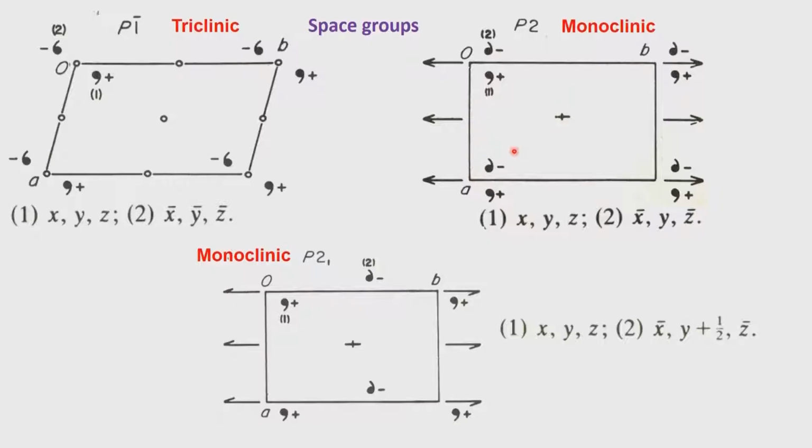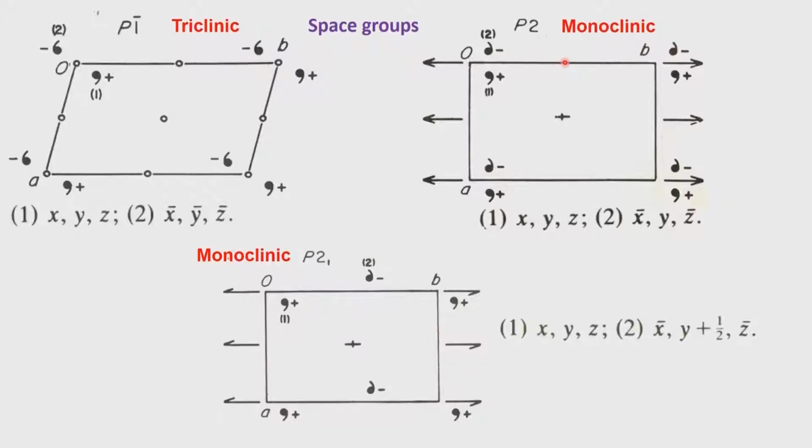In this Z equals 2, we can always have an object sitting on the two-fold symmetry. Suppose you have a two-fold symmetry object, just like the laser pointer here. It is a circular pointer, so it has all kinds of symmetries, and two-fold is also incorporated in it. Suppose it sits anywhere along the length of this axis, you see that half the object on the top and half the object on the bottom are related by a two-fold symmetry. As a consequence, this will be the special position in P2.